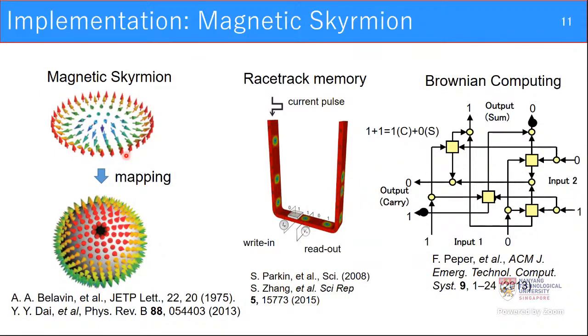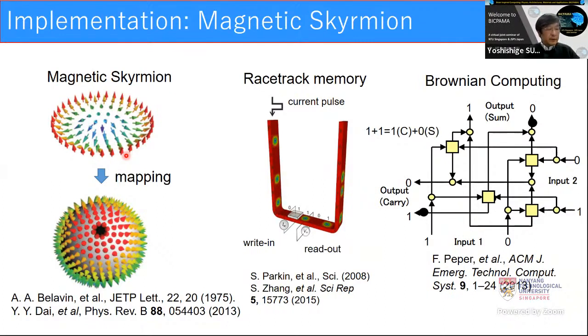For the skyrmion that appears in the ferromagnetic film, we use perpendicularly magnetized film with interfacial Dzyaloshinskii-Moriya interaction. There are Néel type and Bloch type skyrmions, but the skyrmion made by interfacial DMI is thought to be Néel type. That is shown in this picture. If the mapping to the sphere covers the sphere once, the skyrmion number is 1.